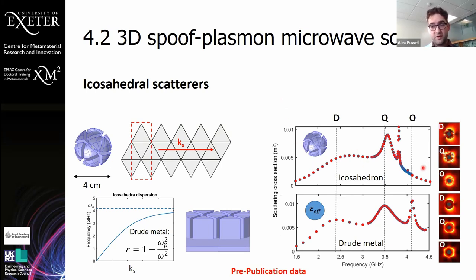We can see we have several modes, and we can do our counting of more mode orders: dipole, quadrupole, and then octopole further up here, although the octopole doesn't quite match up here. But we can see that we have a dipolar field for the dipole, a quadrupolar field for the second mode, and an octopole field for the third order mode. So far, so good.